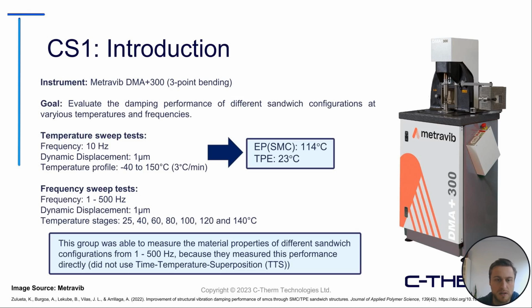But I did want to spend a little bit of time talking about the frequency sweep tests that this group did. So they did frequency sweeps from 1 to 500 hertz with a dynamic displacement of 1 micrometer, and they measured the performance at various temperature stages, at room temperature all the way up to 140 degrees Celsius.